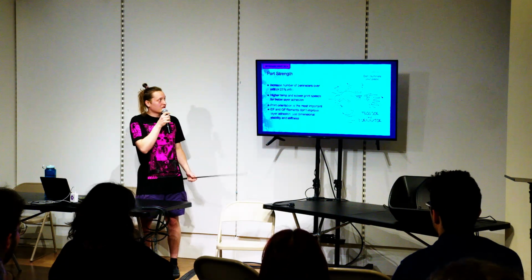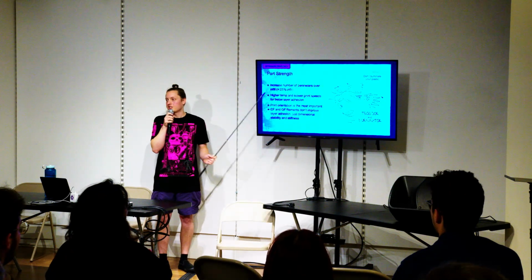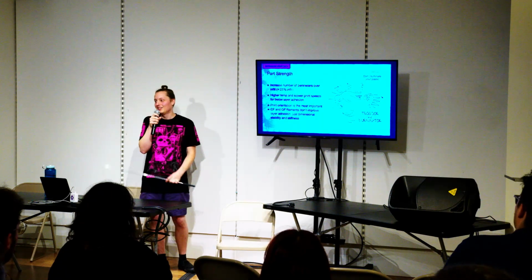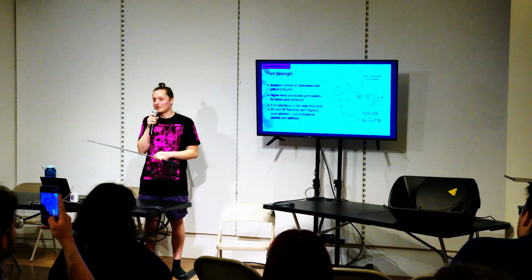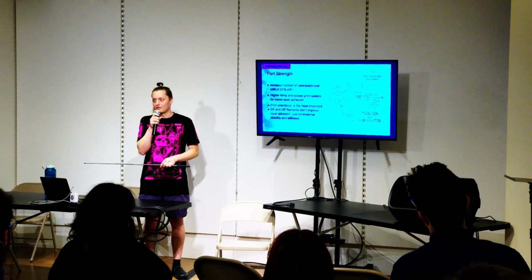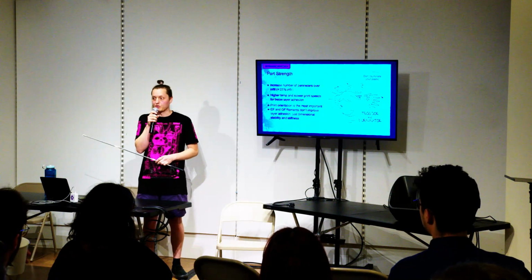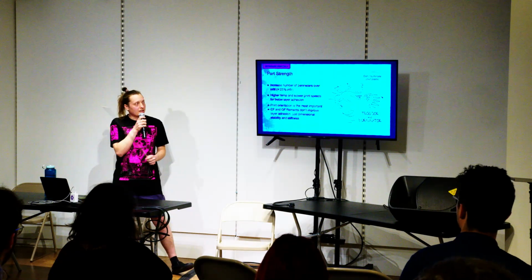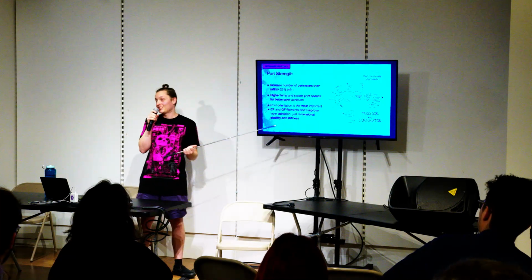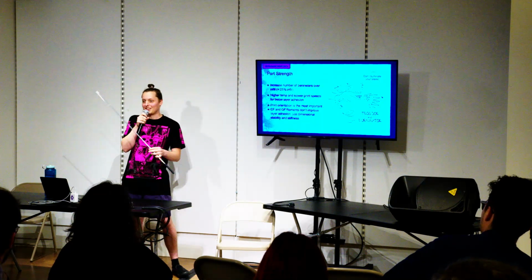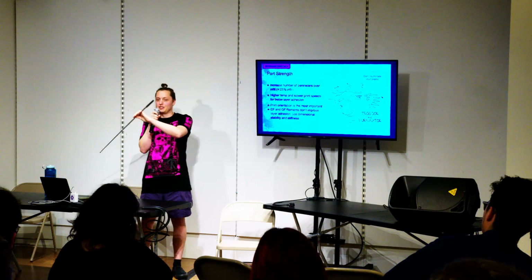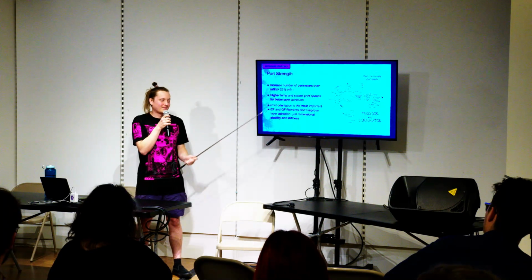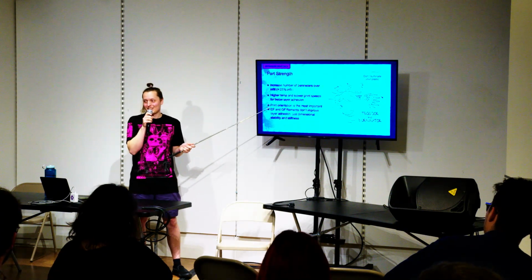Finally, we have part strength. In general, increasing the number of perimeters increases your part strength, and in terms of strength to weight ratio, significantly more than infill does. I generally don't ever print above 25% infill. I just up the number of perimeters. Most of the time I print at 10 to 15% infill. In general, higher temperature and slower print speeds are better for layer adhesion, but if you go too hot, you degrade the material as it's printing and end up with worse results. And as I've kept reiterating, print orientation is the most important.